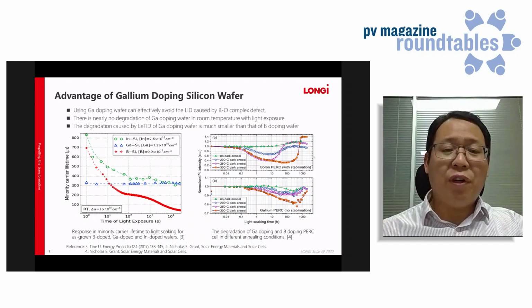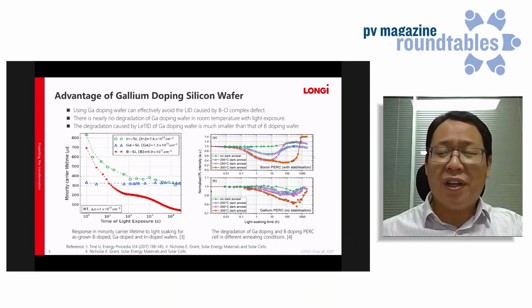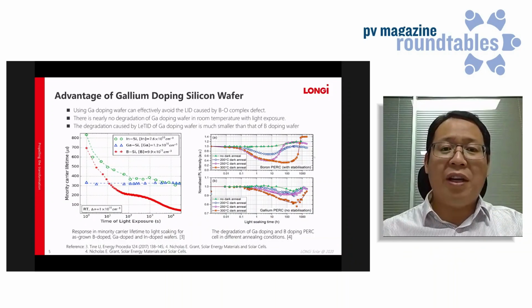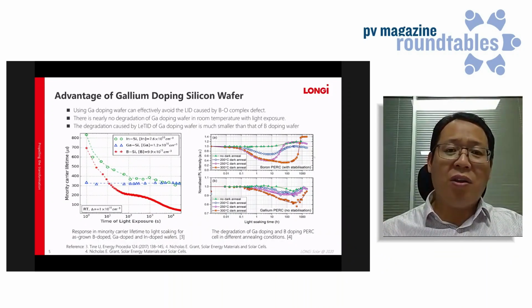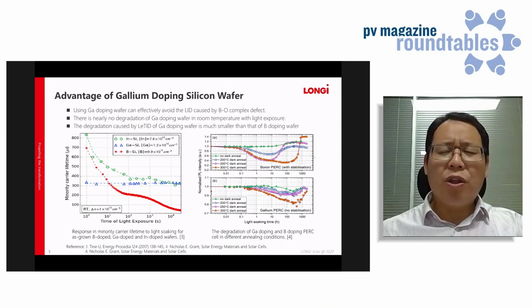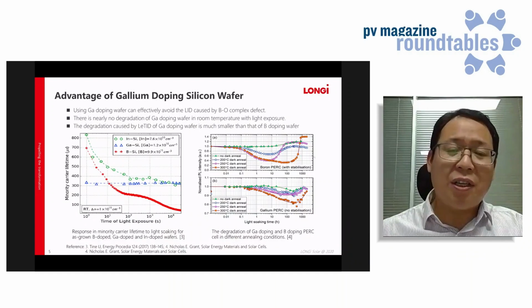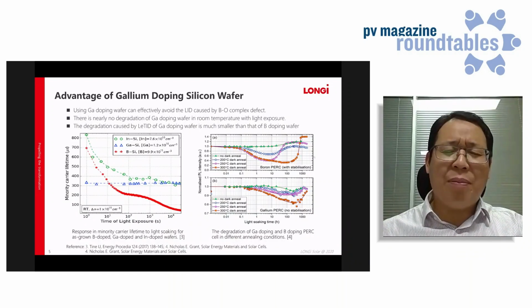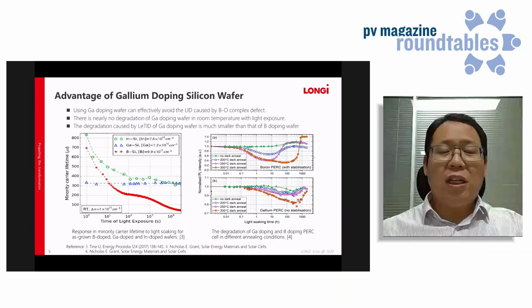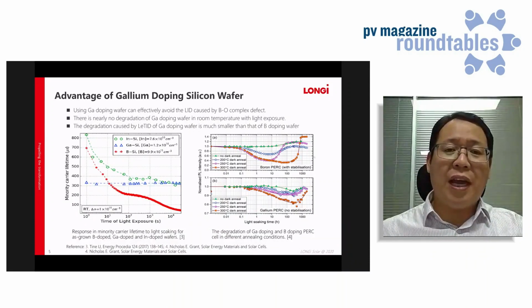But we also find that if the temperature is high enough, we still have some degradation even if we use a gallium doping wafer. The mechanism is not LID, it's related with LETID. LETID, which means light and elevated temperature induced degradation, is some kind of LID occurring at high temperature. The mechanism of LETID is quite complicated. Some research institutes, such as UNSW, think it's related with hydrogen, and some research institutes think it's related with impurity in the silicon wafer. But it means that we need better quality of wafer to reduce the LETID phenomena.